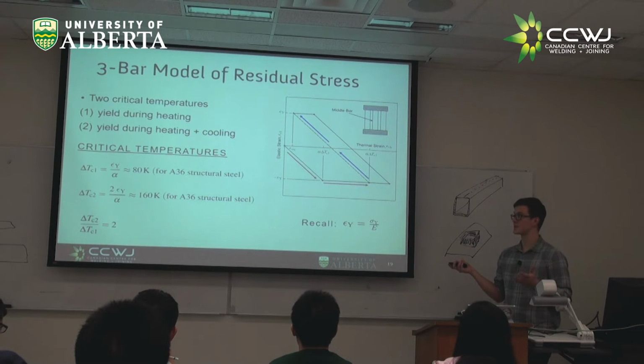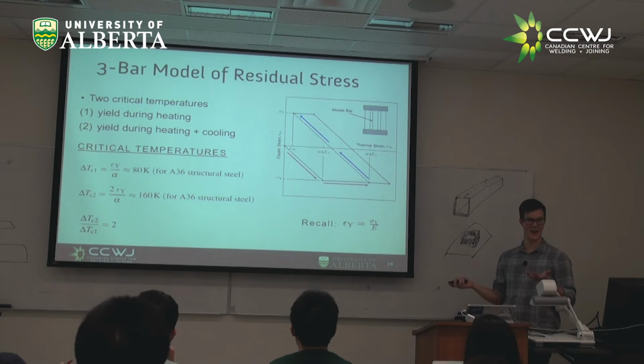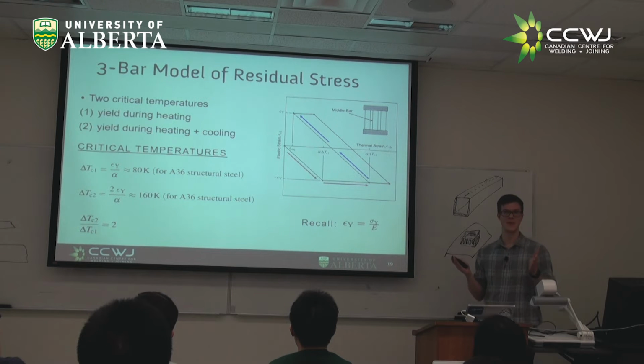And we see for A36 structural steel, our yield stress is about 250 megapascals, elastic modulus about 210 gigapascals, and alpha is about, give or take, 1.2 times 10 to the negative 5 strain per degree Celsius. We can see that we'd have this at about 80 Kelvin. Now what do you guys think? Does that seem low, high? What do you think? In terms of welding, 80 degrees Kelvin seems low, but that's true. 80 degrees Kelvin is all the temperature change you need to start creating stress.